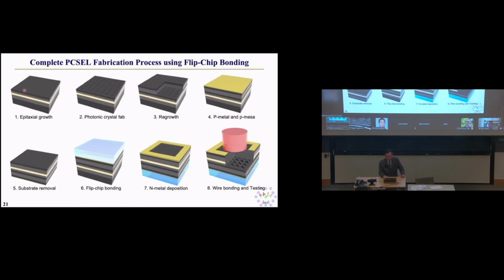So we grow up to the quantum well, to the cladding, the photonic crystal layer. Then we pattern it to form a two-dimensional photonic lattice using e-beam lithography and RIE etching process, creating nanoscale holes essentially on the semiconductor surface. And then we do a regrowth. We put the material back into the epitaxial chamber to complete the whole structure, including the cladding and the contact layer on the top. So basically, I form the whole laser structure.